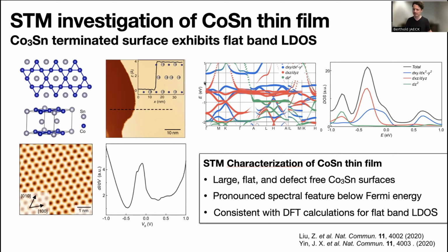Of course, we're not the first ones to do that, and also people before studied this compound here using DFT calculations. Essentially, what you find is that the multi-orbital nature of your cobalt atom, having dxy, dx squared minus y squared, dxz, dyz orbitals, and so on, gives rise to a relatively large set of bands. The important part is now when you focus just below Fermi energy, where you can find this Kagome flat band. Well, it turns out it's not completely flat, in this case, because of the out-of-plane interactions and spin-orbit coupling. However, we'll show in the following that the electrons are quite localized regardless.